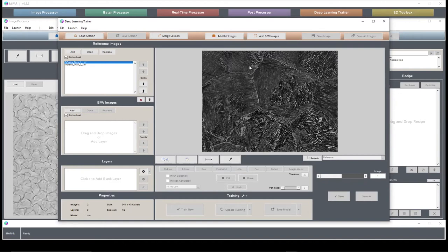This is a problem that a week ago I still thought was impossible to automate. We've tried everything classically to recognize only these features. Our brain seems to do a fantastic job at recognizing that particular pattern, but there's no grayscale intensity difference between what's on the boundaries and the interior. There's only this very abrupt change in local pattern, typically accompanied by what's called grain boundary alpha, these stringer features along them that tell a material scientist these are grain boundaries. But it's still done purely manually today, unless you use a technique like EBSD to measure the orientations. And the goal, especially in industry, is to automate this from optical microscopy. And that can have a huge impact on all sorts of value aspects.